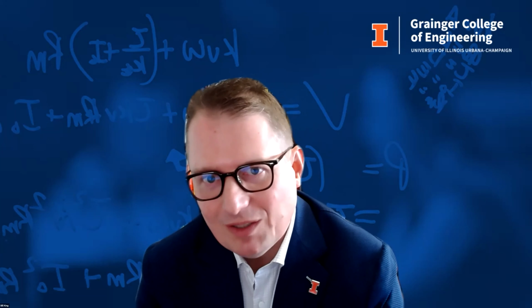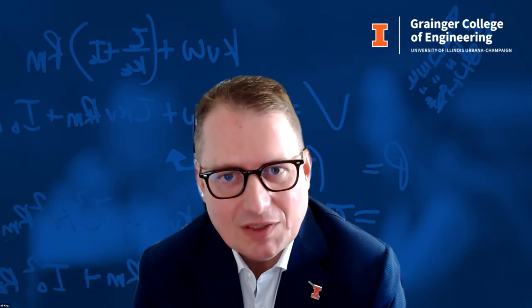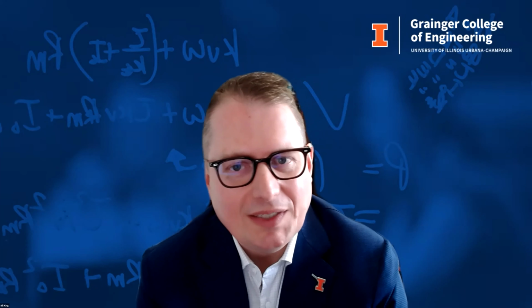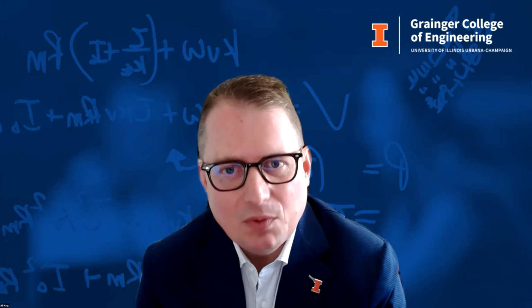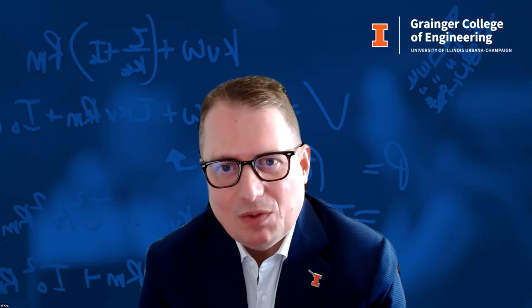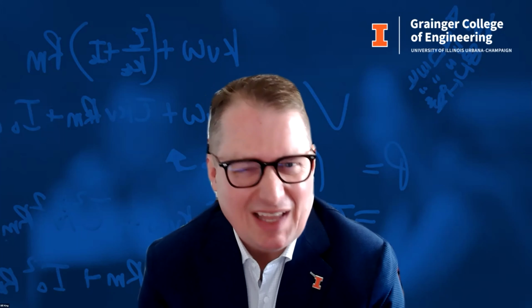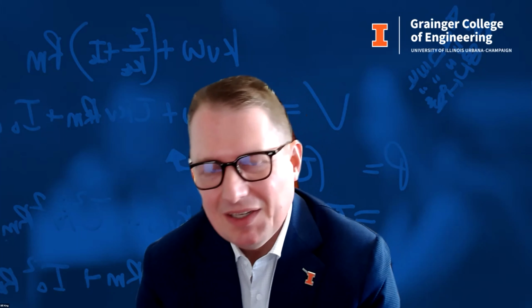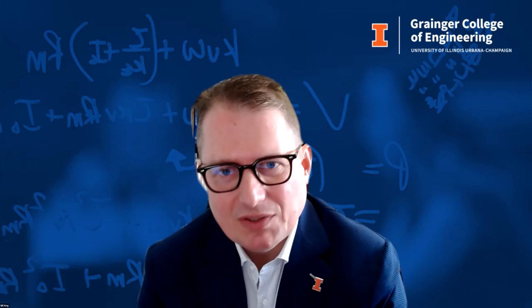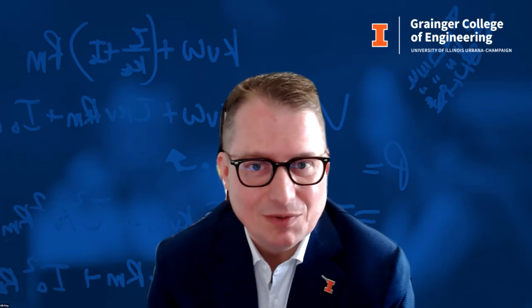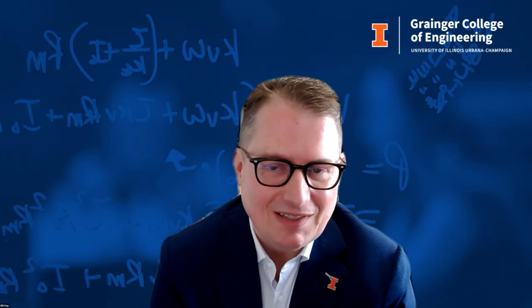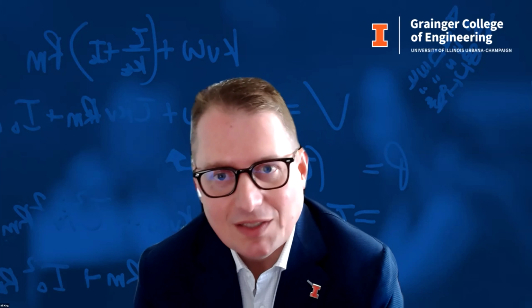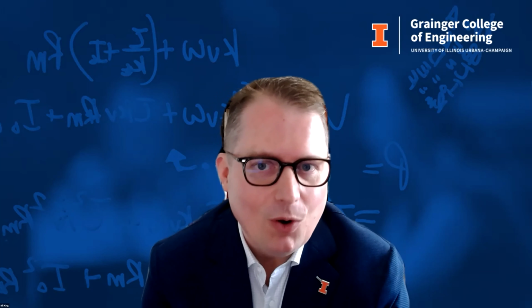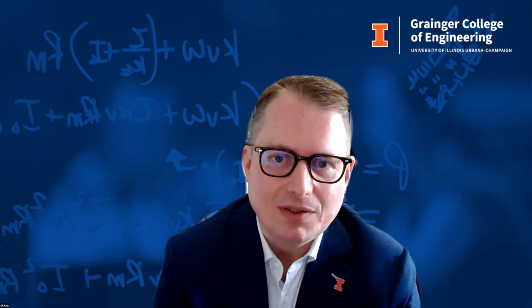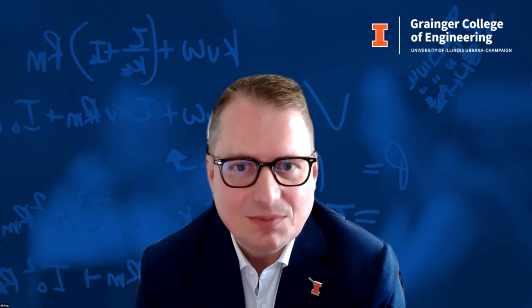In fact, there's some work in the literature that shows that the roughness of metal additive parts affects the flows in unusual ways. There are some strange issues with slippery boundary conditions on those rough metal additive surfaces, because they also have a little bit of porosity. That seems to affect the flow physics, especially at higher flow rates. So that's an opportunity for more R&D to sort out what's going on. But as you point out, of course, you can do post-processing that would smooth the surface. There's a host of metal additive technologies out there that would allow you to get the surface that you want with the right treatments.